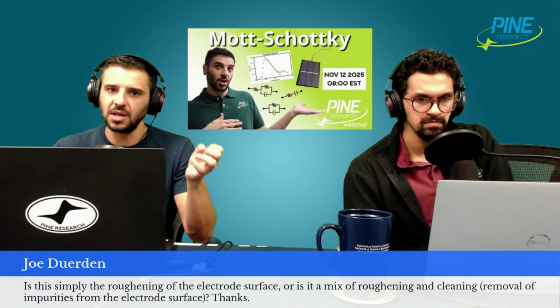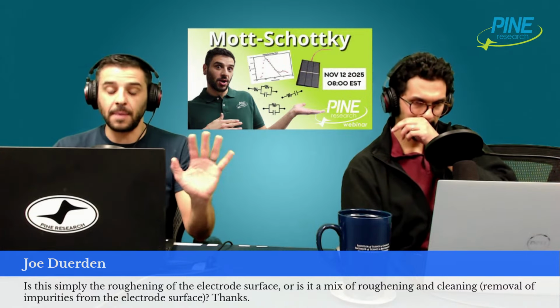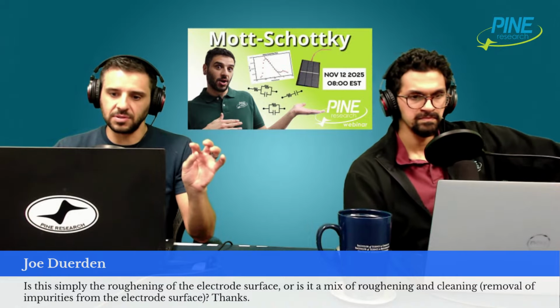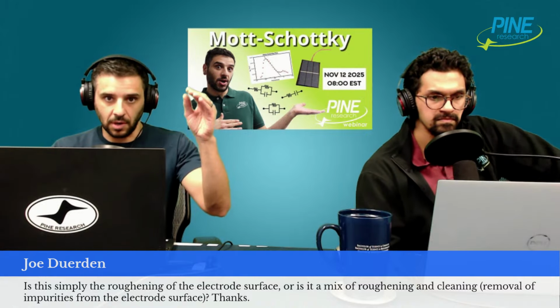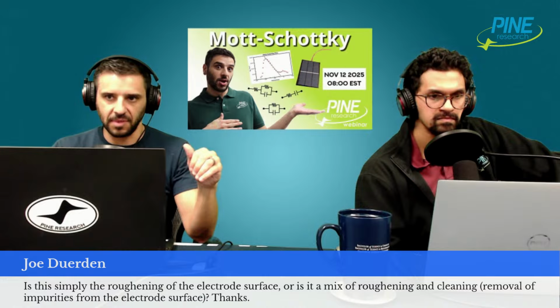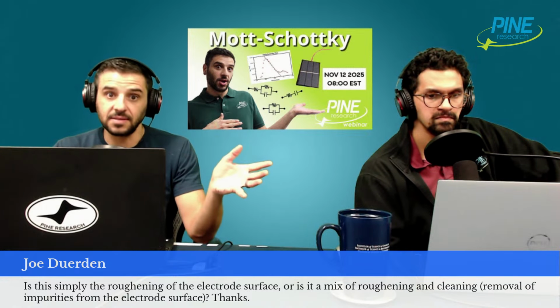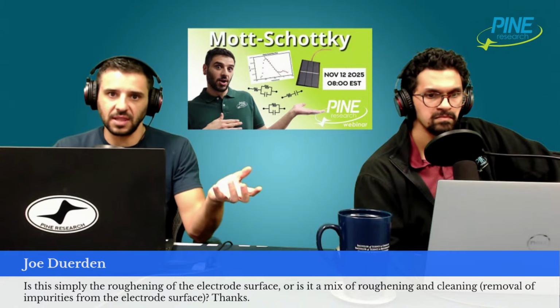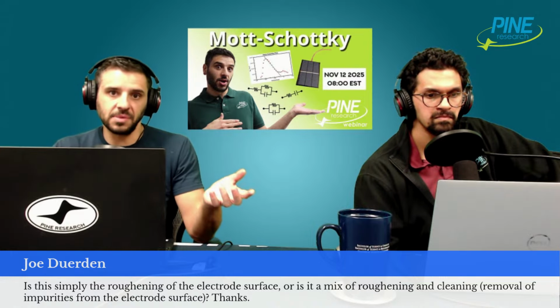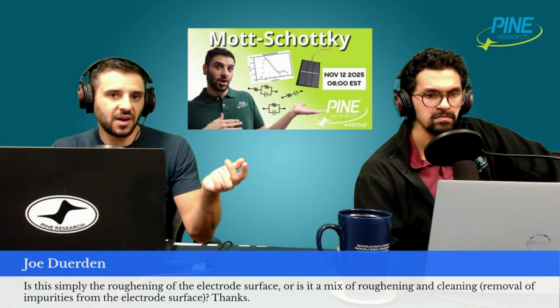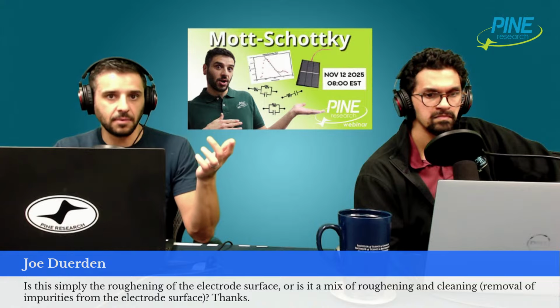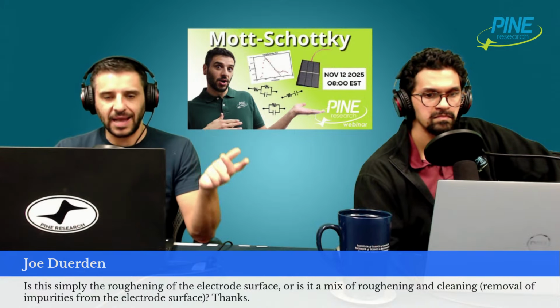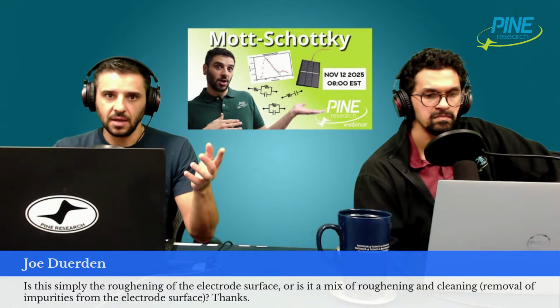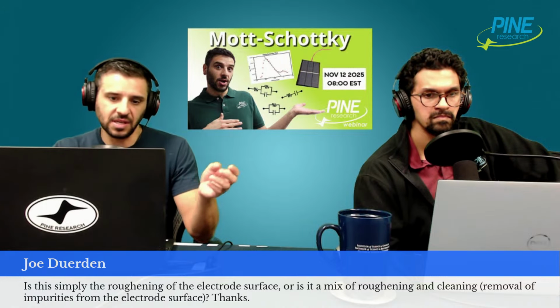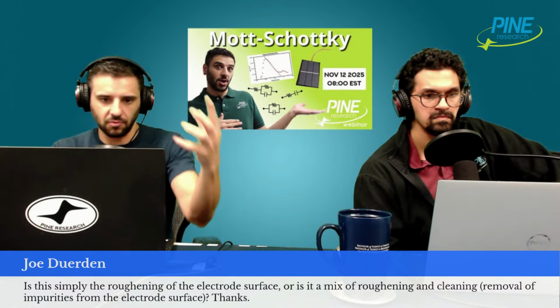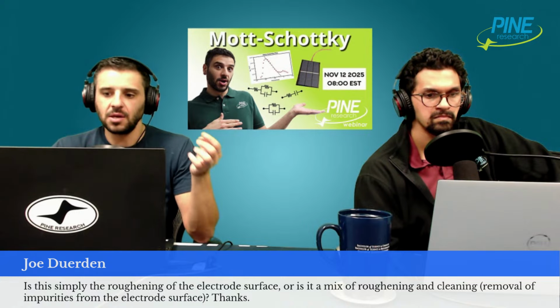It's not exactly certain. That being said, it is at least reasonable to suggest that if, for example, after a bunch of CVs, the alpha value has dropped from like 0.9 to 0.6, I'm just making up numbers, one of the arguments you could make is that an alpha of 0.6 indicates the surface has gotten more rough. My capacitive effect has become less ideal because the surface is now more heterogeneous or rougher. That would be one way, in theory, you could do that.